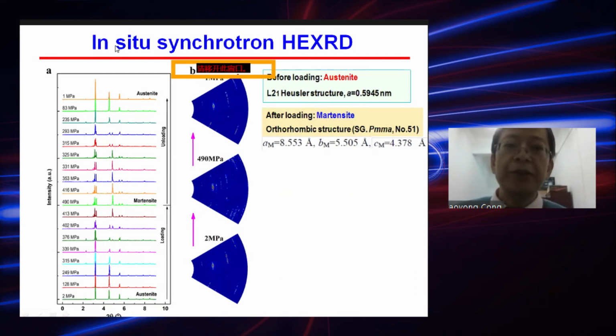We use in situ synchrotron high-energy X-ray diffraction experiments to trace the crystal structure evolution during loading. These are the diffraction patterns at different stress levels. We find that before loading, it is in the austenite state with the L2_1 Heusler structure with this lattice parameter. And after loading, it becomes martensitic. It has an orthorhombic structure with this space group and this lattice parameter.